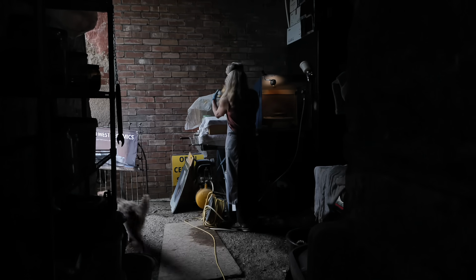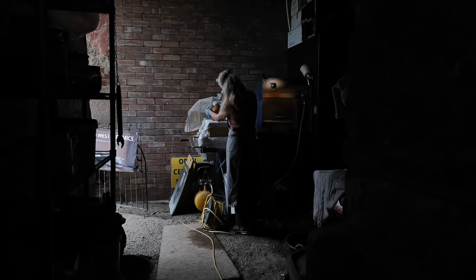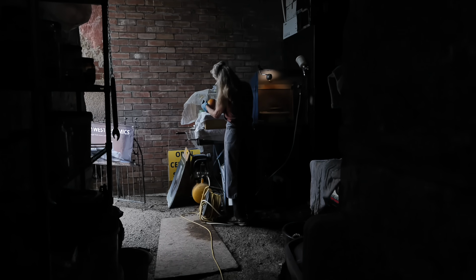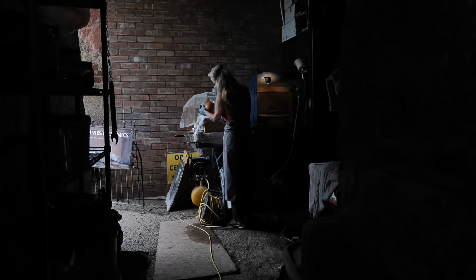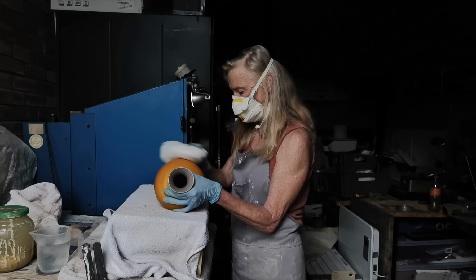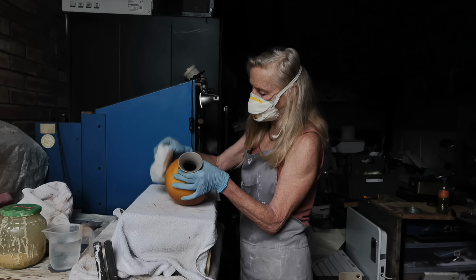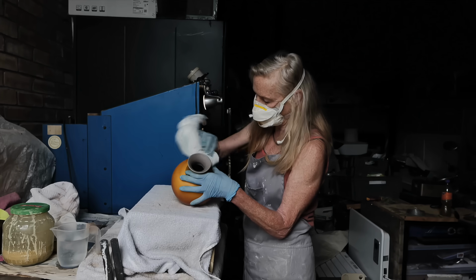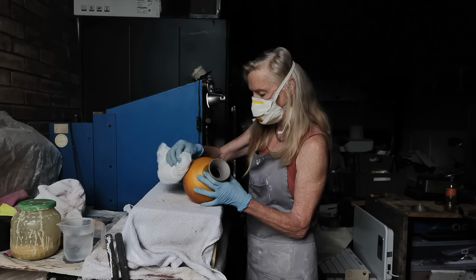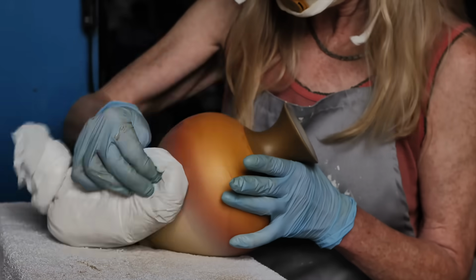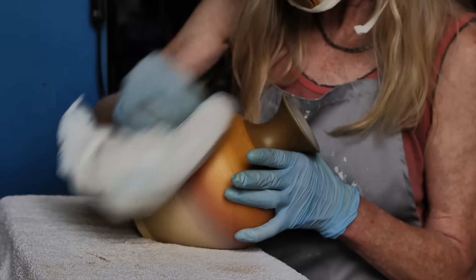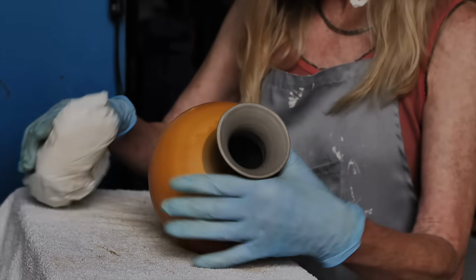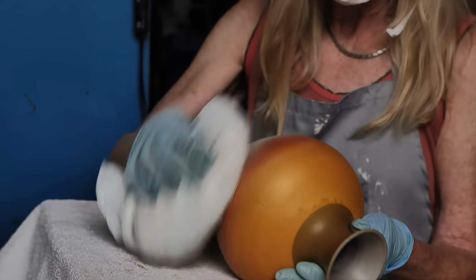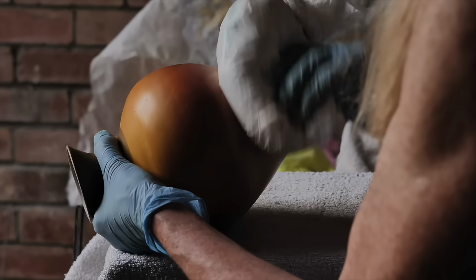Once they've been sprayed onto the pot, they're then polished. They're such fine particles that a gentle polish with a sponge inside a plastic bag or a microfiber cloth will bring out the sheen. Once I've applied all the different terra sigs, it's left to dry and put through a bisque firing. I fire to 980. I go quite slowly, between 65 and 80 an hour to 600, and usually a hold, around a 20-minute hold.